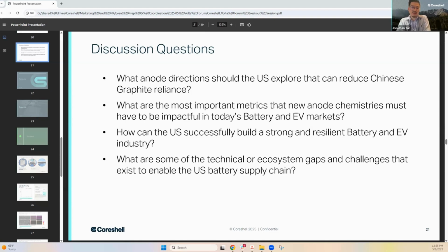Long term, we want to be a silicon anode active material supplier. We don't want to be a gigafactory producer ourselves. But we think it's important to demonstrate at a full cell level in a representative cell that can be manufactured at a reasonable scale. Because otherwise, you're trying to convince a very mature, now more mature industry that's built up at scale to take on a chemistry risk. That's really not going to be something appetizing for them until you've de-risked it to a very large degree. So completely agree with your assessment. That's why we're only talking about data as it relates to full cell applications.